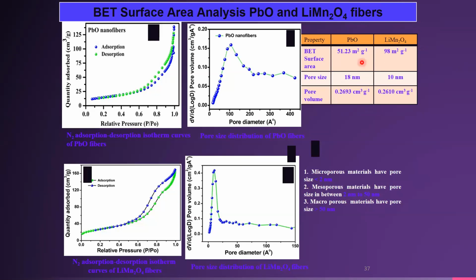The lead oxide nanofibers have a BET surface area of 51.23 meter square per gram, and the lithium manganese oxide nanofibers have a high surface area of 98 meter square per gram, with pore volumes of 0.2693 centimeter cube per gram and 0.2610 centimeter cube per gram respectively.